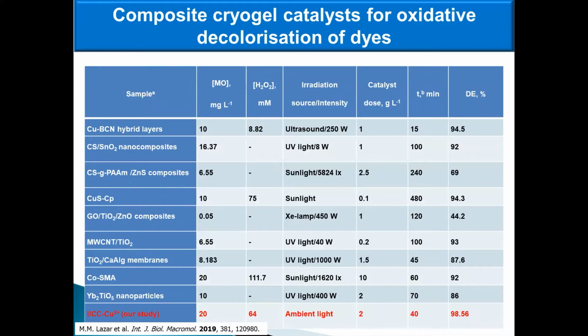In this slide I have summarized some literature data on methyl orange degradation by various systems in comparison with those obtained in our study. Almost all the parameters selected as optimum conditions for our catalytic system are more effective than those of the previously reported methods. Thus, a higher methyl orange concentration, mild reaction conditions, pH 6, and a small amount of catalyst and co-catalyst led to a decolorization efficiency of about 98% within 40 minutes at room temperature and under ambient light.